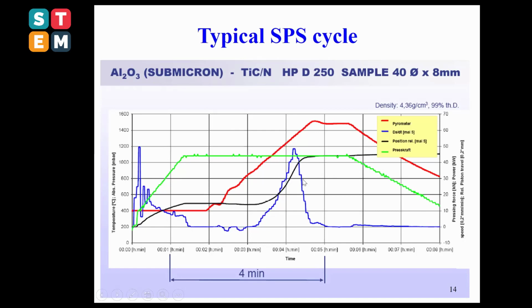But the blue one here is the derivative curve. The speed of the black one shows that the maximum is in the middle of the inflection point of this black curve. This is basically the sintering temperature of the material when you want to optimize all this.